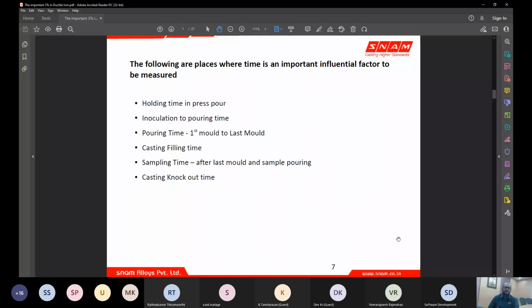As I had mentioned, all the reactions are time dependent, and when you leave your treated liquid metal at the same temperature, or as the temperature keeps dropping, your time keeps increasing, the reaction keeps happening, and you don't get benefit out of it. Magnesium is going to react with oxygen and sulfur, and it is going to be lost by itself. So our target should be, before it loses its maximum potency, let us complete our casting. Let us fill all the molds available before all these losses happen. If any delay happens before filling of the mold, you are losing the potency of your process. That means your nodularization treatment would have given some efficiency, but you are losing it because we are delaying during the process.